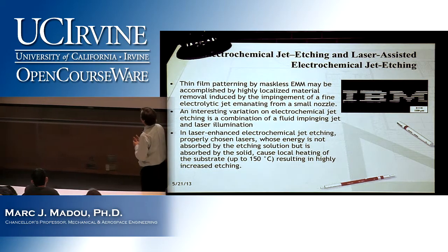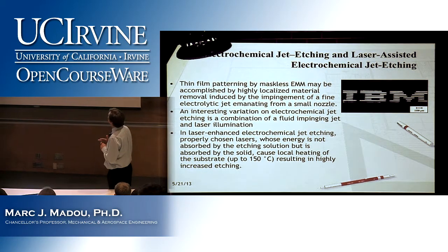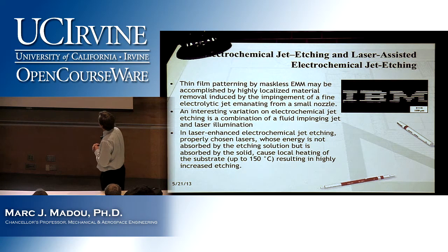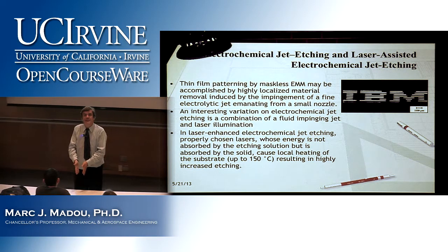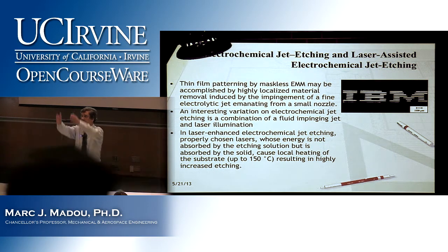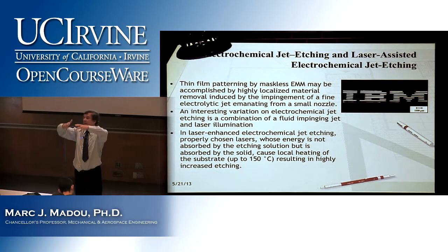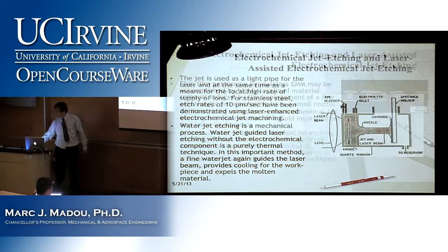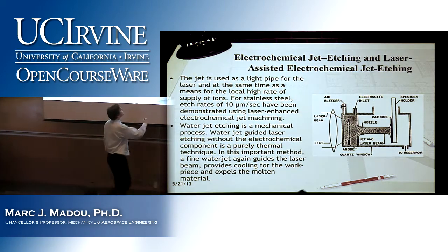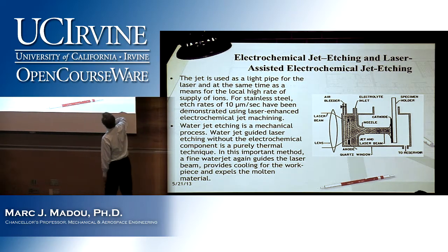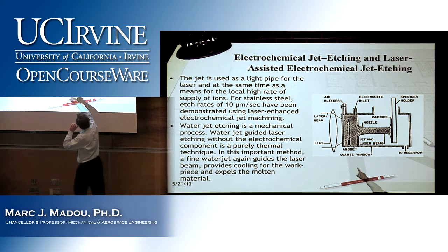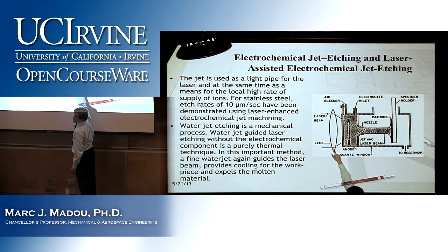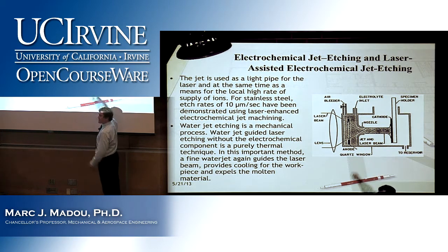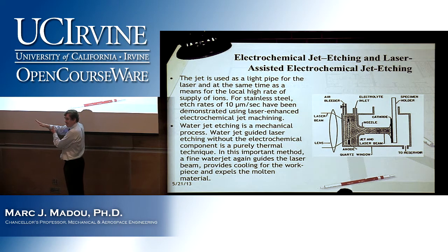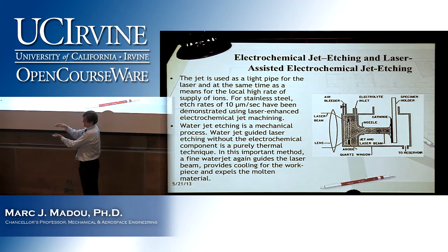So thin film patterning by maskless ECM may be accomplished by highly localized material removal induced by the impingement of a fine electrolyte jet emanating from a small nozzle. The next thing we're going to do is combine this liquid jet with laser machining, so that liquid can act as a waveguide. In that waveguide, I'm going to put laser light. This was also developed at IBM. This is a specimen that I want to etch. This is the nozzle, same as before, except in this case, with a lens, I focus a laser beam into the liquid stream, and you make it such that the laser beam does not emanate from the jet, so it acts like a waveguide.